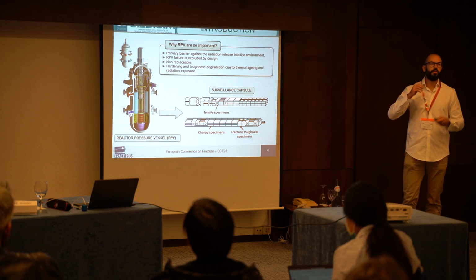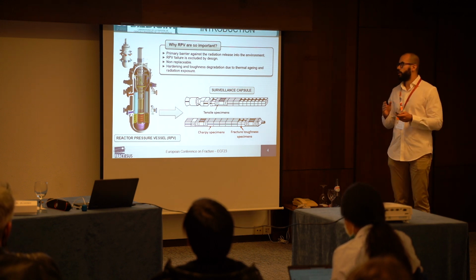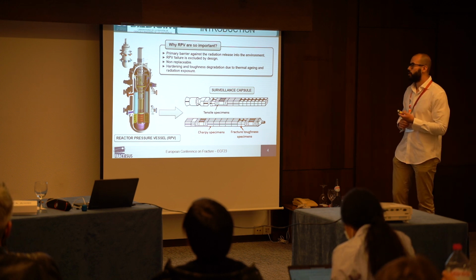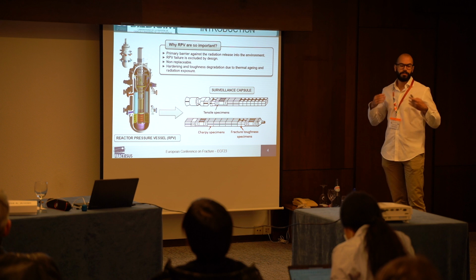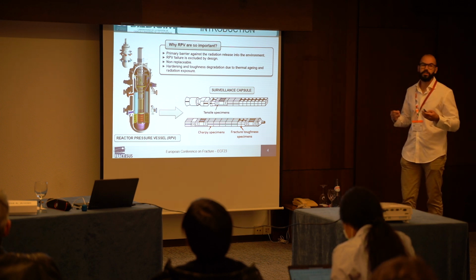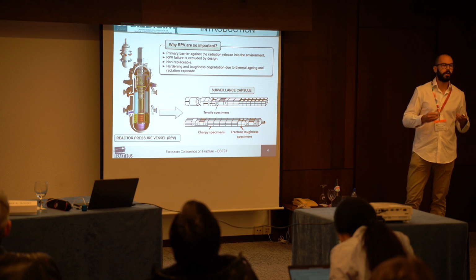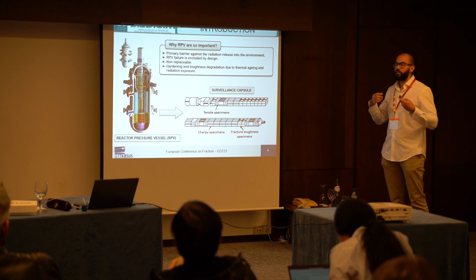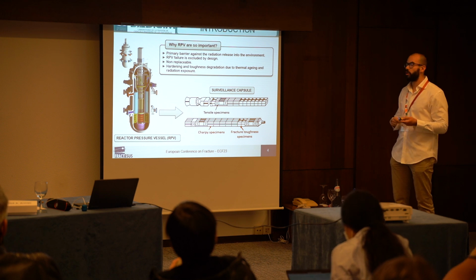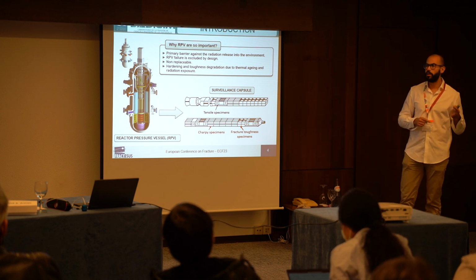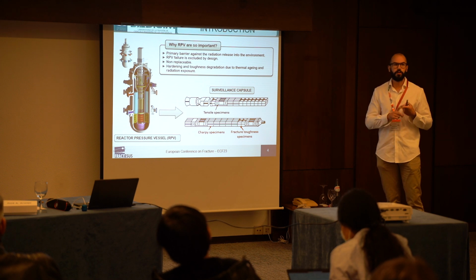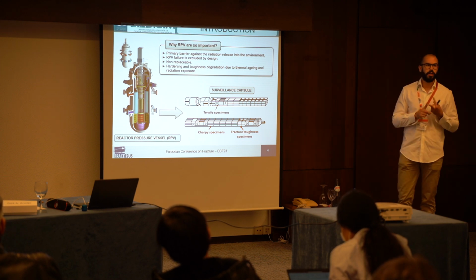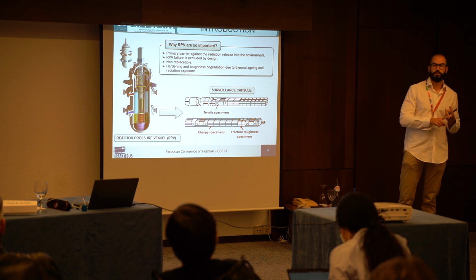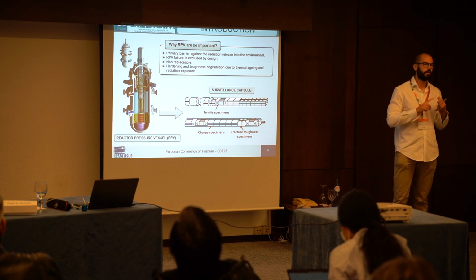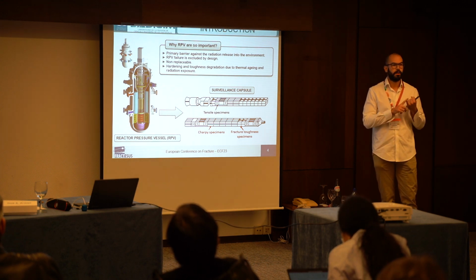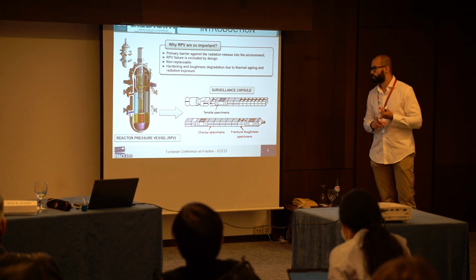So, if we pretend to extend the safe operation of the nuclear power plants, one of the most important things to do is ensure the structural integrity of the reactor pressure vessels. This huge component is really important for several reasons. It's the primary barrier against the release of irradiation into the environment. Its failure is excluded in normal or accidental scenarios by design. It cannot be replaced, or at least it's really difficult, and it suffers from thermal aging and irradiation exposure.